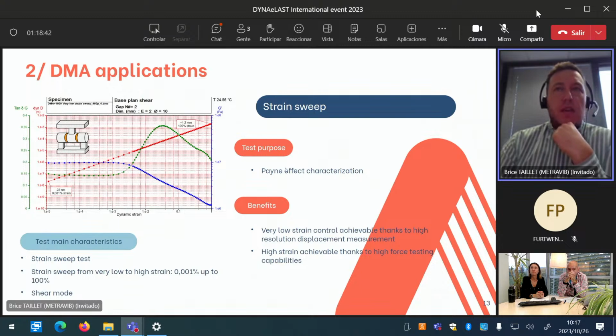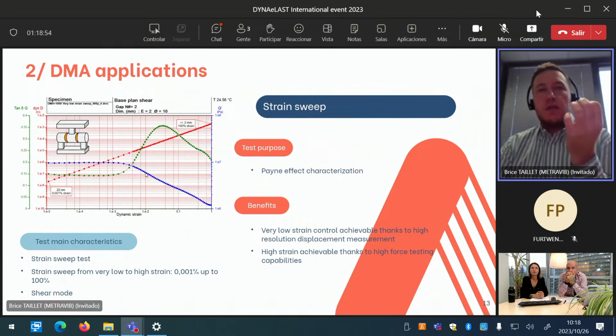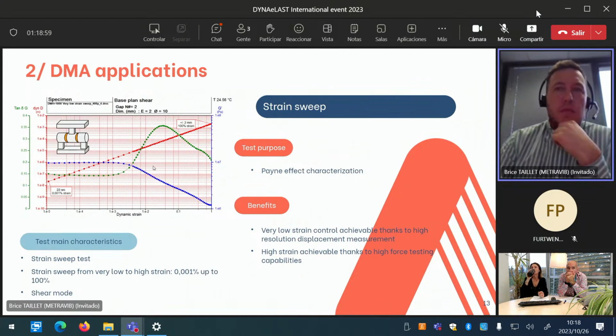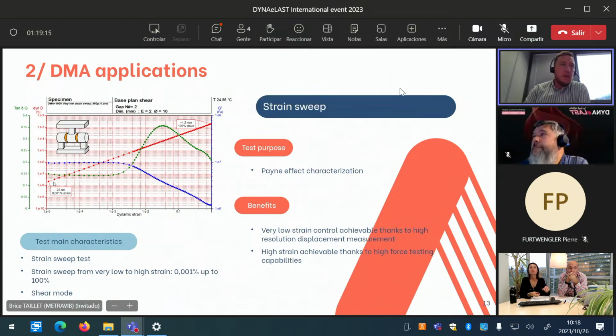One other important test in DMA is strain sweep, and strain sweep is to visualize, to characterize the linear behavior or the non-linear behavior of the materials. And the non-linear behavior, as you can see, we can name it the Payne effect. And of course, if we are able to characterize the Payne effect, we are also able to characterize the Mullins effect. So in red, you have the dynamic displacement applied by the DMA. Very low displacement, plus or minus 22 nanometers, and at the end plus or minus 2 millimeters. And as you can see, we have a linear behavior and we have a non-linear behavior. And if we are looking at the green curve, we also observe a maximum of tangent delta as a function of dynamic strain.